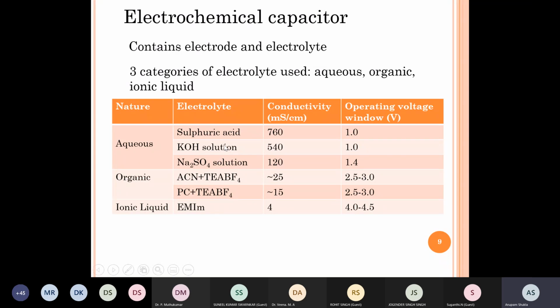And so, just briefly looking at the categories of electrolyte used, there are aqueous electrolytes, organic solvent based electrolytes, and ionic liquids. And these are the three commonly used electrolytes. Sulfuric acid, at 760 millisiemens per centimeter, has the highest conductivity, but again it is much smaller than the electrodes. Then we have 6 molar KOH solution at around 500 millisiemens per centimeter.